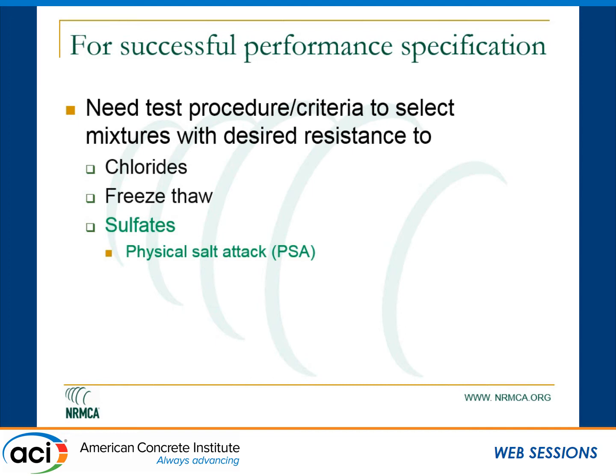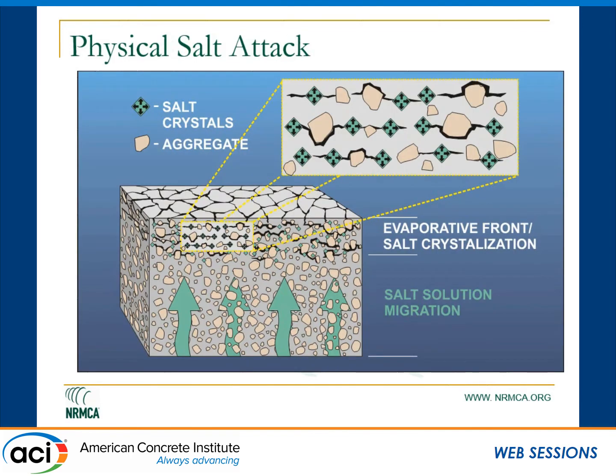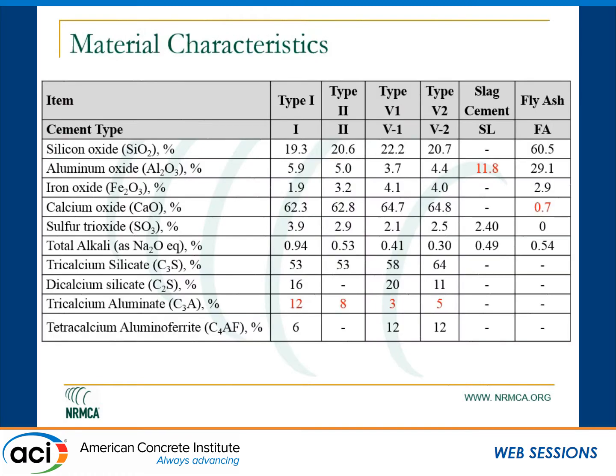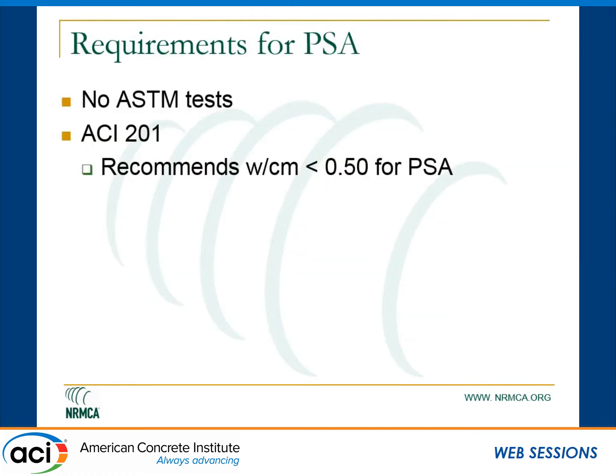Carl covered the chemical sulfate attack. For physical salt attack, you have salt solution mainly coming from sulfates in groundwater or other salts. When it comes to the surface, the water evaporates and you have salt crystals crystallizing. Because of variable temperature and humidity, you can have cracking which looks more like a scaling type of failure. If you look at our codes and standards, there's really no ASTM standard for this particular failure mechanism. In ACI 201, we currently just say a water-cement ratio less than 0.50 for physical salt attack.